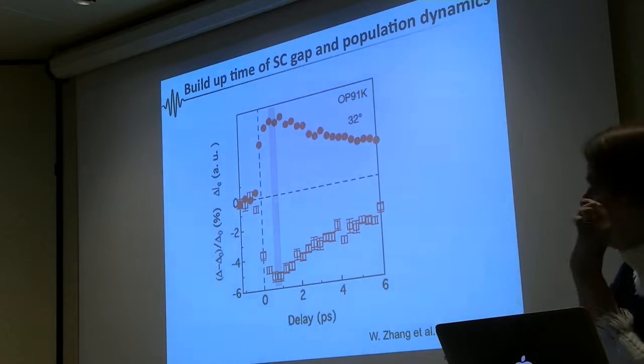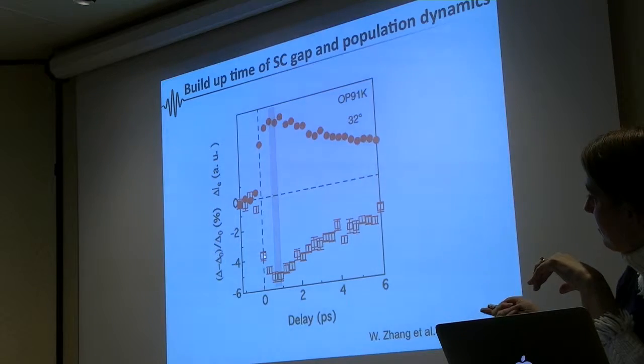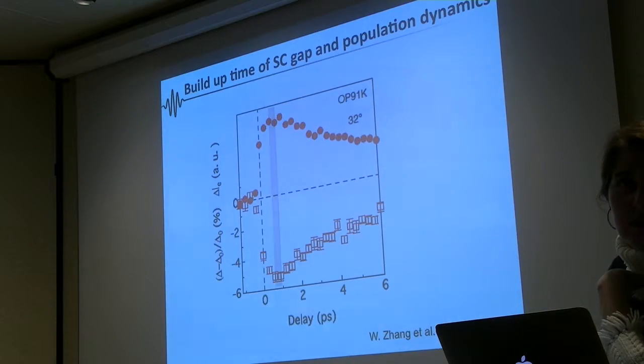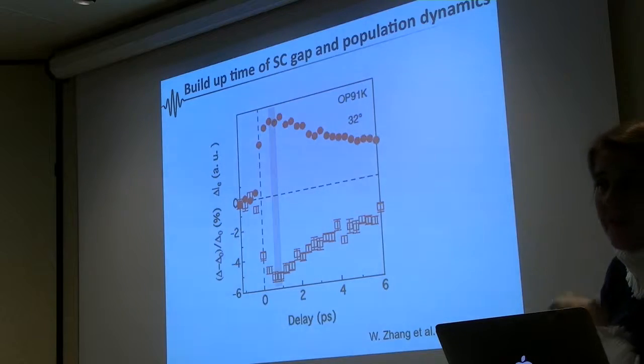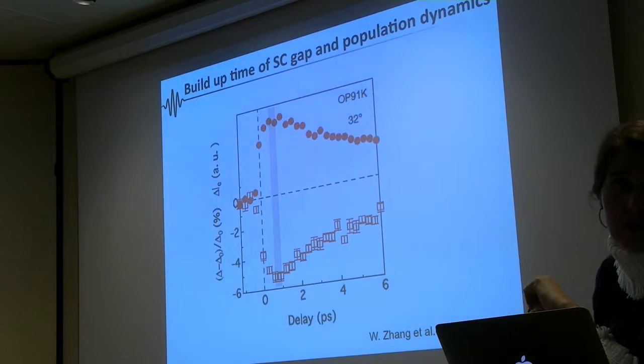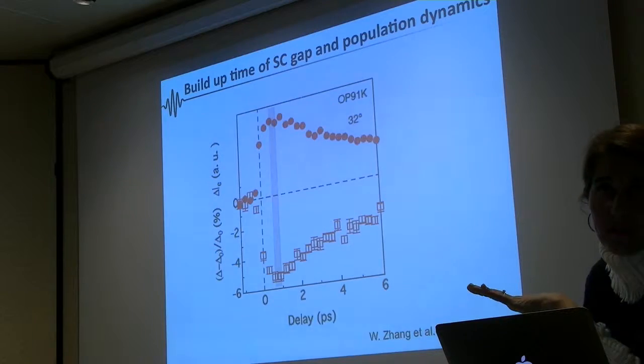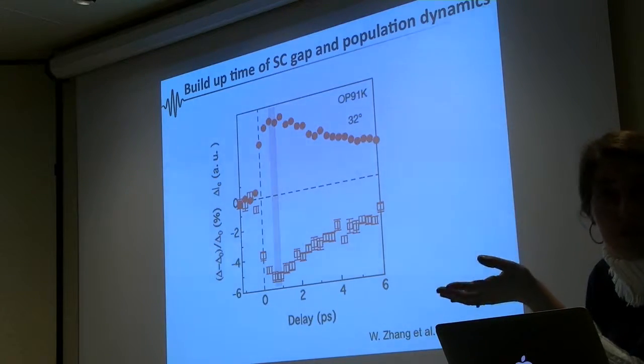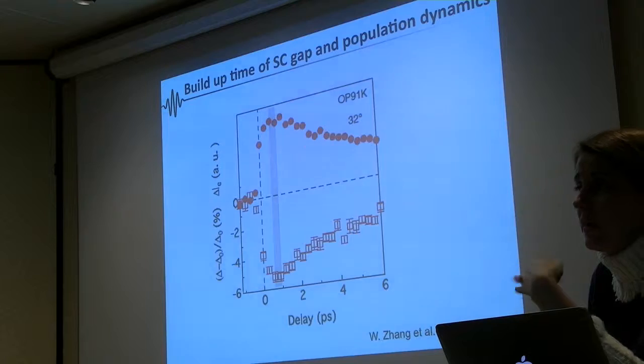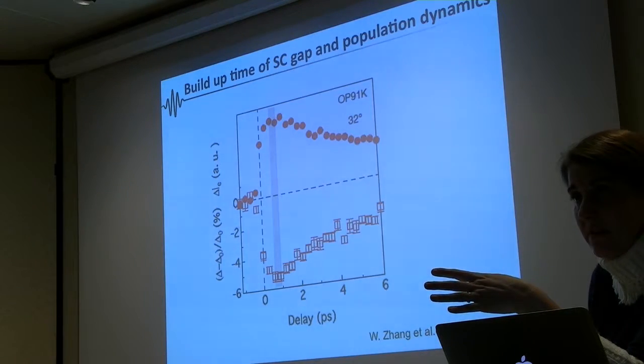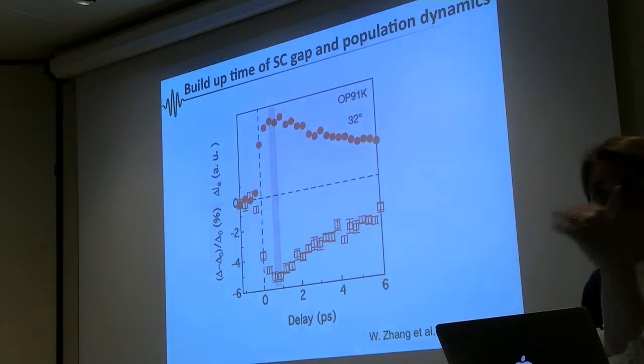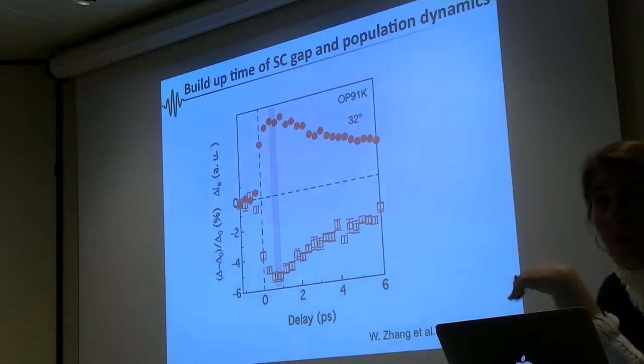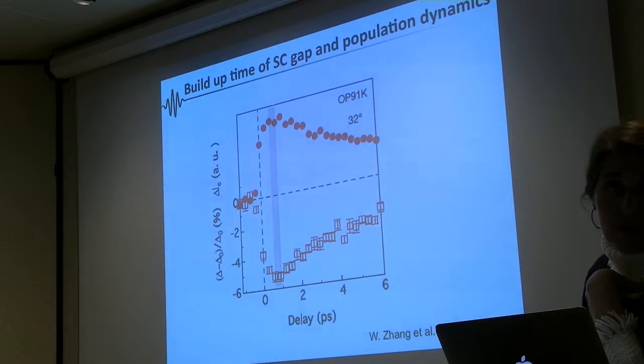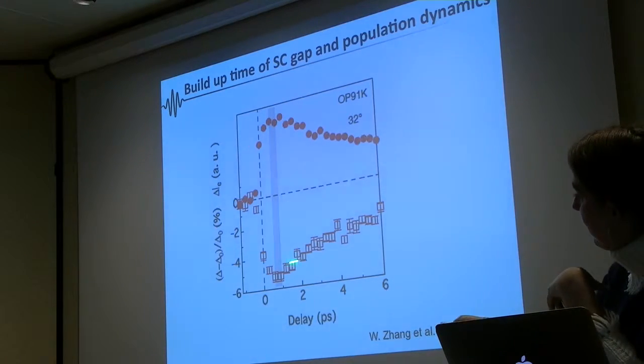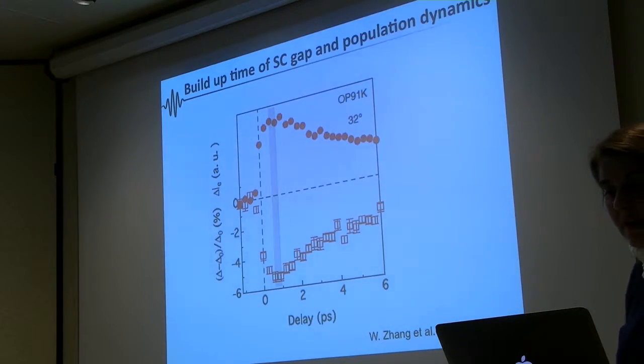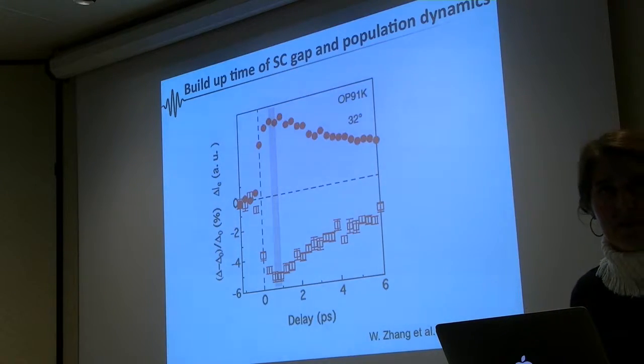But if I look at the moment at t equals 0, my gap just starts to respond, it doesn't respond right away. And if I do this experiment for a conventional superconductor, within the fluence I can access, so 4 microjoule, which is the minimum I can go, the response is almost immediate. Although now there are some optical experiments where you can go to lower fluence, and they show that they actually see something very similar. So there is something that happens in this regime which seems to be, obviously, not an immediate response of the system.